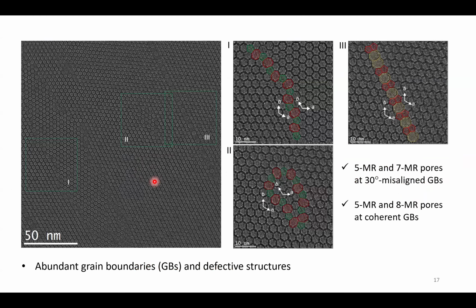In addition to the bulk structure, we also see abundant grain boundaries and defects in this COF. For example, as you can see here, there are 5-membered pores and 7-membered pores along the boundary between two grains with a 30-degree misorientation. And there are double 5-membered pores and 8-membered pores along the coherent grain boundaries. These observations remind us of graphene, which has similar grain boundary structures, albeit on an atomic scale. Here we are at nanometer scale.